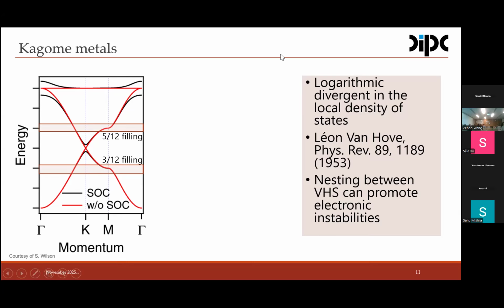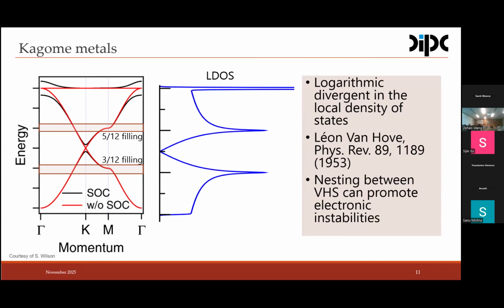is mostly when the chemical potential falls at the Van Hove singularity, 5/12 filling and 3/12 filling, because here we actually have a high density of states. The energy spectrum develops a logarithmic dependence of the density of states, which drives the formation of charge density waves and other broken symmetry orders. In particular, this high density of states can drive the nesting between Van Hove singularities, and can promote electronic instabilities, like, as I mentioned before, the charge density waves.